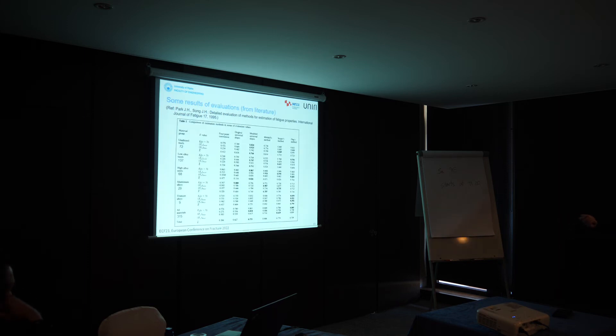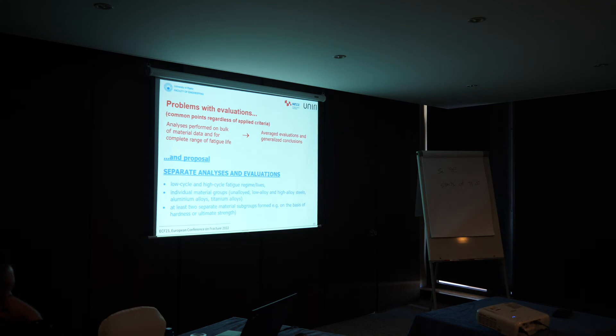We are using these criteria in our analysis. One important observation is that methods A, B, or C can result in exactly the same value of error criteria — the same percentage of data within the scatter band — but they can be very different in their actual performance and ability to capture experimental data. This additional information is often disregarded. Furthermore, we noticed that in all analyses performed so far, only the bulk of material data is used and analysis is performed for the complete ranges of fatigue life, which results in significant averaging — you get one number, but you don't know what's behind it.